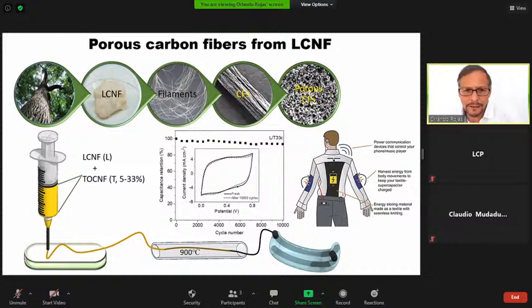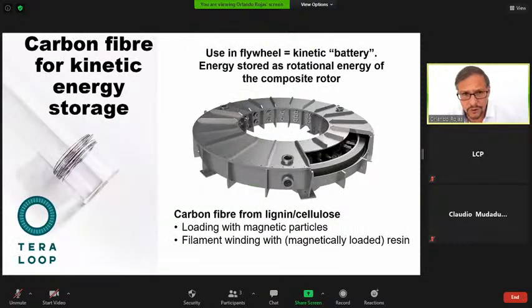And again, the capacitance with cycle numbers is shown here. And just to say that the electroactivity is quite interesting. One of our former students in the group is now working in this area in a company called TeraLoop. It's a new company. And they are looking into carbon fibers that need to be also magnetic. And those magnetic carbon fibers are really special for integration in so-called flywheels.